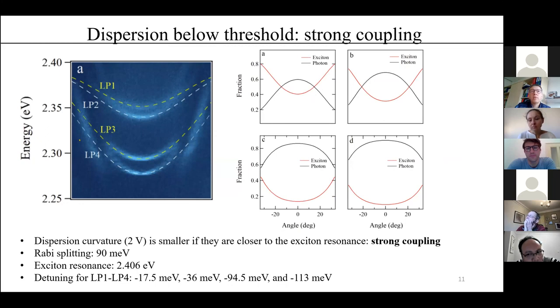Because strong coupling is something which typically we would like to observe, like the change of the curvature at high K, high momentum. But in those systems, this is similar to the system with parallel polarization, in that there is a change of the refractive index that's due to the dispersion because of the presence of exciton. So there's a question about how you're sure about the strong coupling in the system.